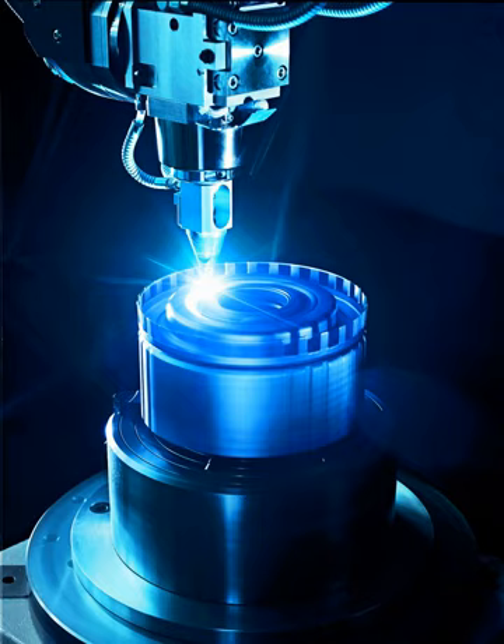Pump light can be used more efficiently by creating a fiber disk laser, or a stack of such lasers. Fiber lasers have a fundamental limit in that the intensity of the light in the fiber cannot be so high that optical nonlinearities induced by the local electric field strength can become dominant and prevent laser operation and/or lead to the material destruction of the fiber. This effect is called photodarkening. In bulk laser materials, the cooling is not so efficient, and it is difficult to separate the effects of photodarkening from the thermal effects, but the experiments in fibers show that the photodarkening can be attributed to the formation of long-living color centers.